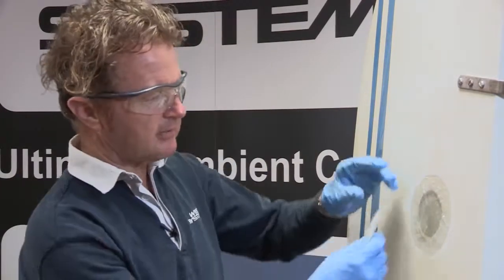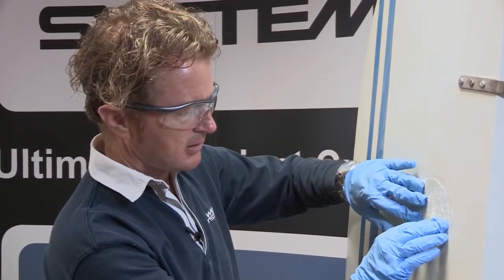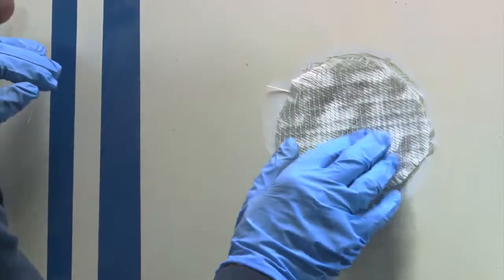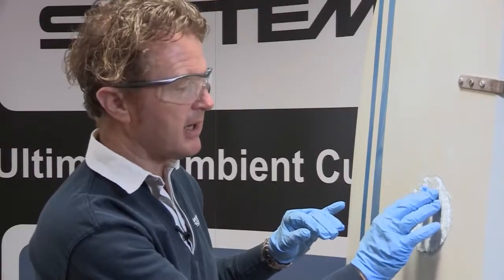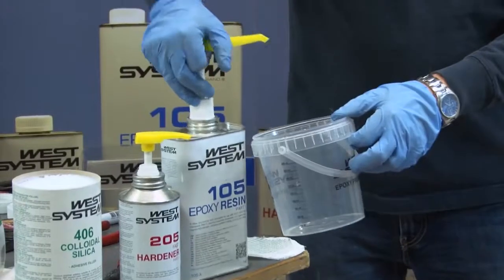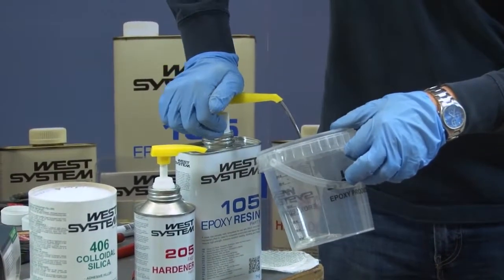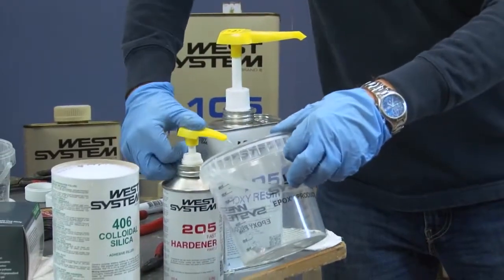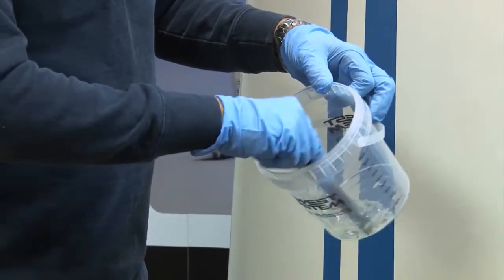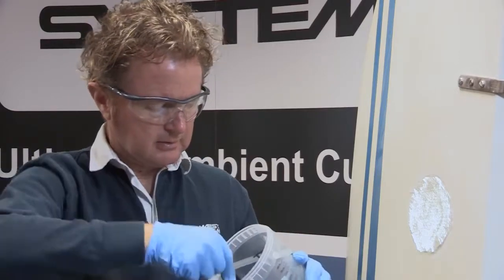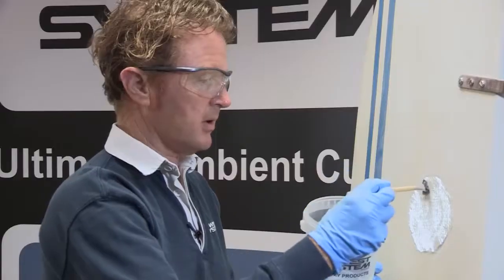I'm now conducting the structural part of the repair, so I'm adding my four different size discs of biaxial glass fabric. I'm going to start off with the biggest disc, which we mentioned was very, very important, and I'm going to place that over my repair like so. And you see how it sticks there quite nicely, and it's actually starting to wet out as well. I'm now going to make up another mix of epoxy. One pump of resin, one pump of hardener, blend the two together thoroughly. I'm going to use a brush again to wet this out.